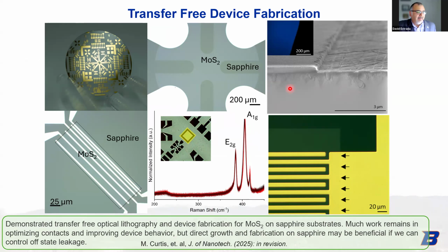One of the other things we've done recently is develop our own photoresist, so we can do photolithography directly on sapphire. We have a contact aligner here at Boise State, and when we do contact alignment through transparent substrates, the UV will reflect off the aligner and re-expose your photoresist, and you don't get the good resolution that you're targeting. So we have a UV blocking layer in our liftoff resist now that allows us to pattern these TMD films directly on sapphire. It may not be great for device applications because the sapphire really dopes the film, and you can't get good offstate leakage, but for optoelectronic devices or other types of devices patterned directly on sapphire, this approach will work quite well.